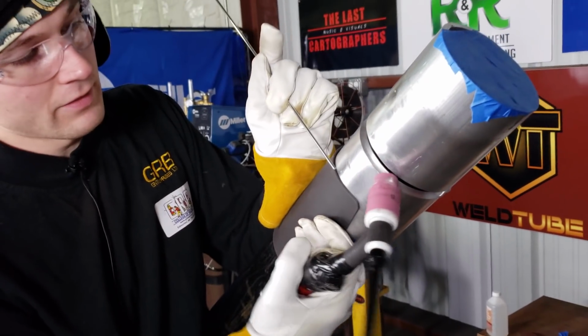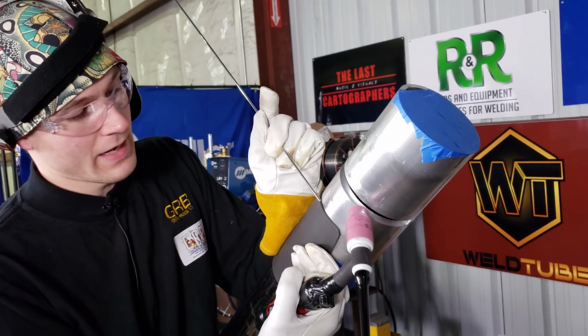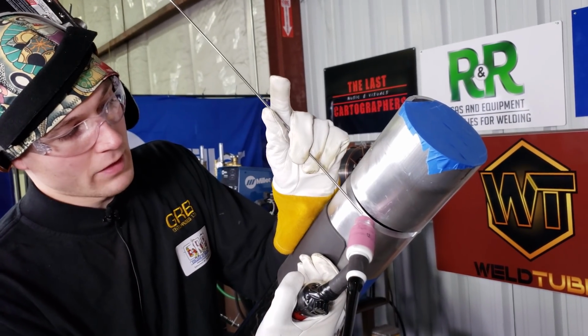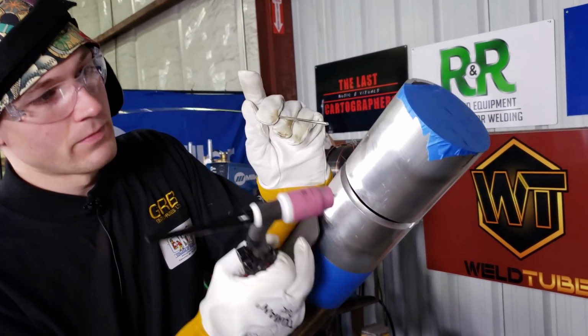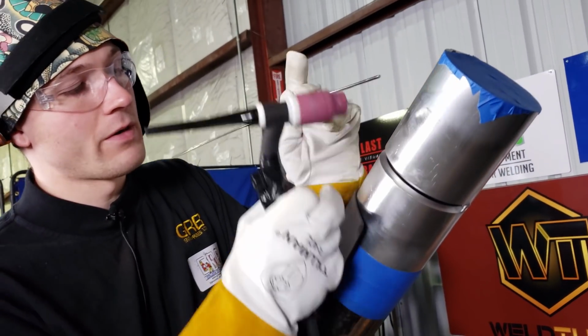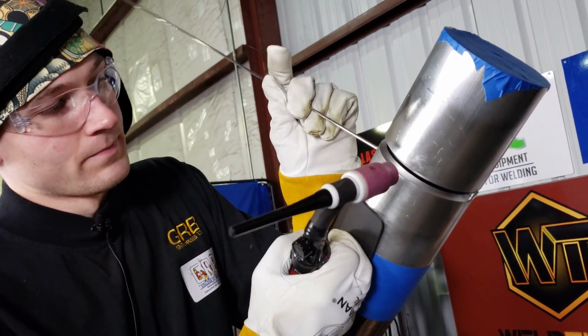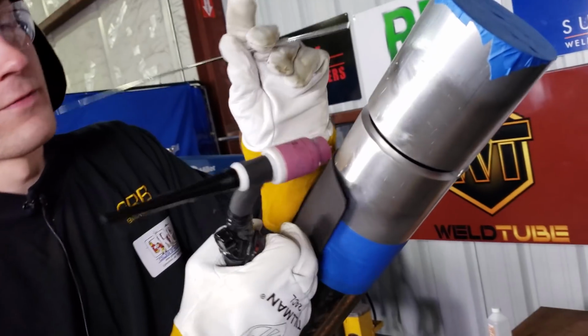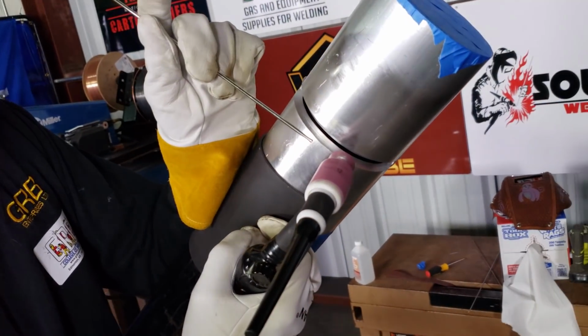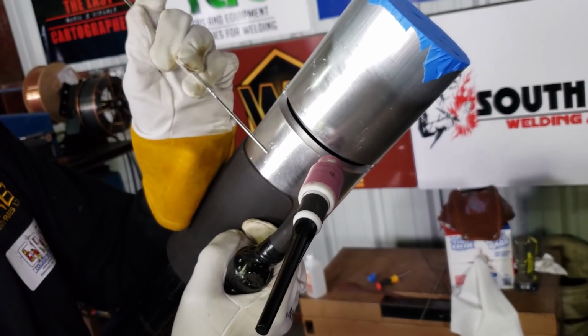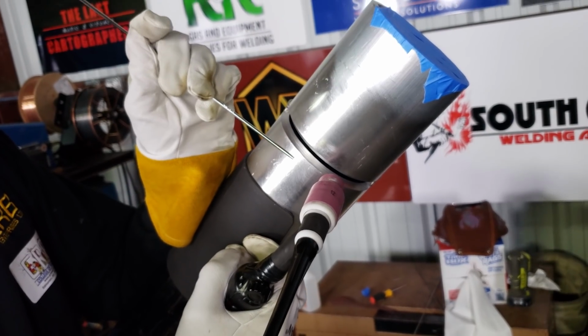Also, if you're holding the torch at an angle, not perpendicular, when you start adding the filler metal close to the weld puddle, the tip of the filler metal is going to ball up, oxidize very badly, and droop down. This is very oxidized, very rough metal. There are two things you can watch out for to see if you're holding that torch perpendicular.